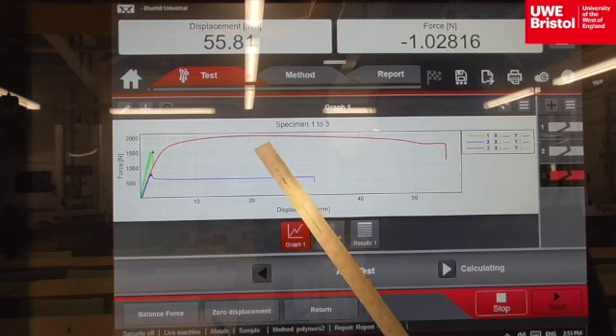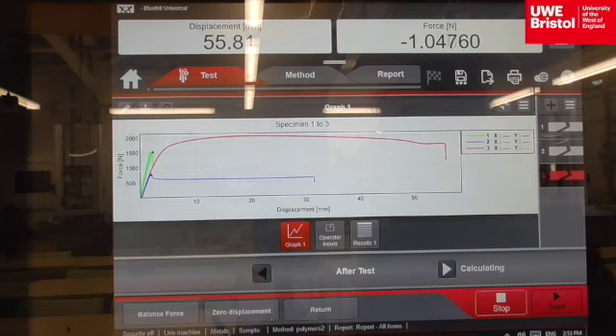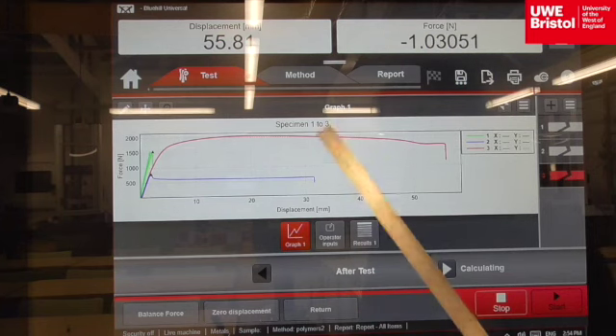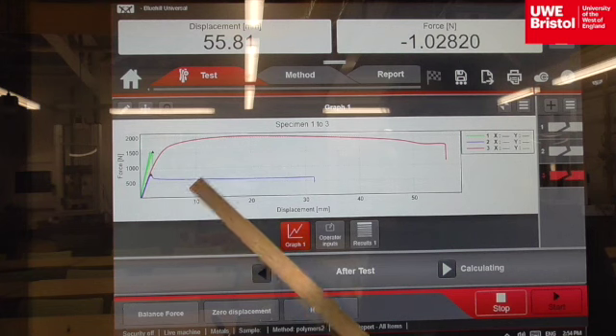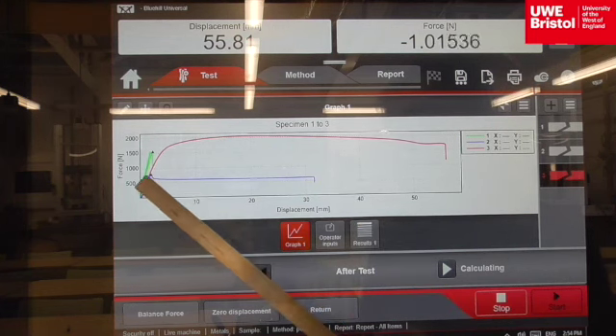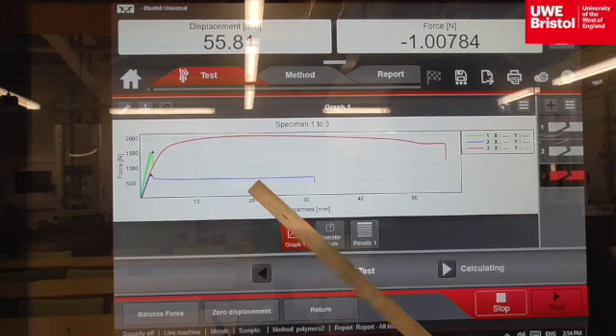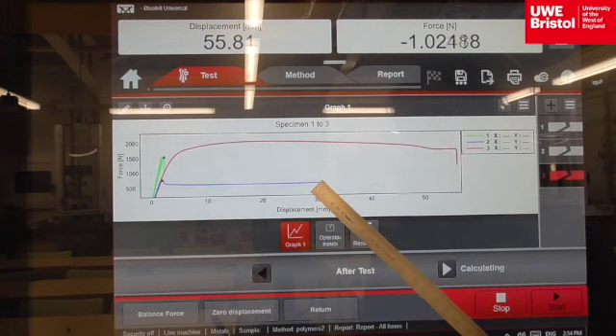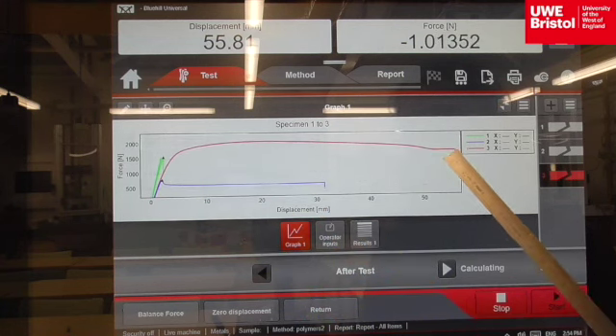From the graph, nylon has a greater maximum load than the polystyrenes, so it is expected to have a higher tensile strength when the calculations are done for its properties. It's got significant elongation here, and the area under the graph denotes large toughness properties. For the nylon and the high-impact polystyrene, just before fracture, they show an increase of force required to maintain the rate of extension.